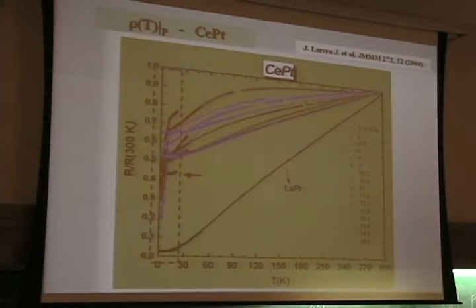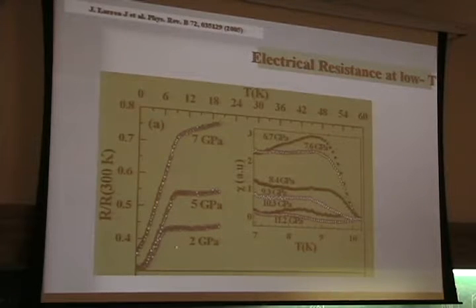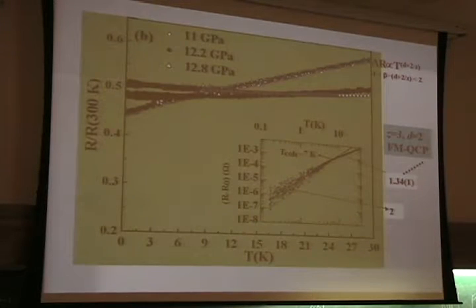Okay, and then here we have the cerium platinum with the pressure, and you see how it evolves. The transition temperature is going down, and here there is also some susceptibility measurement that was done by Professor Eichler in Braunschweig, and you see that the transition goes down, but the shape of the curve doesn't change very much. Only the temperature is going down and the signal is decreasing.